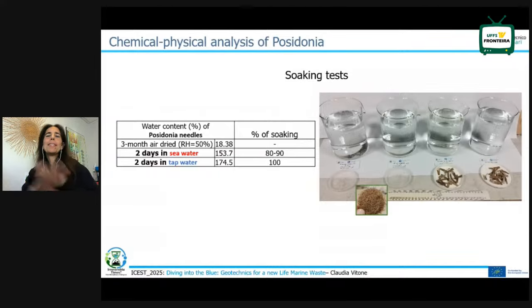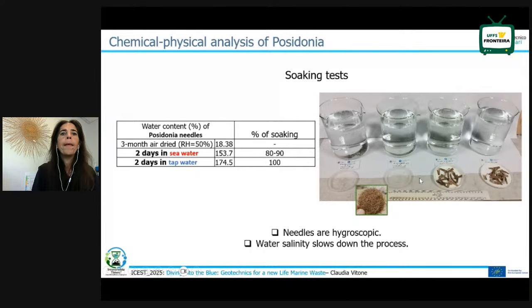So first of all, we started from scratch. What we did at the beginning was to put these fibers in the water. They were floating at the beginning. Then after some minutes, or 2 days at the end, we could observe and monitor that they were going down, they were soaking. They were soaking in particular when they were in tap water, but in salt water, so in seawater, the soaking was a bit slowed down. So this already suggested to us that they were porous in some way, so they are hygroscopic, and water salinity is slowing down the process.